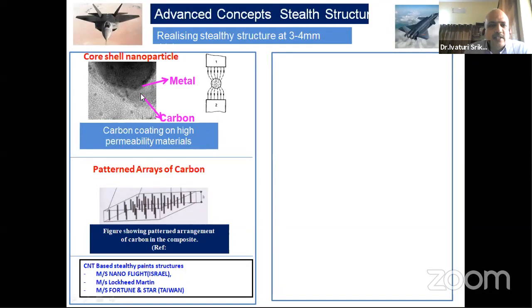Now the latest trend is core shell nanoparticles, where the metal, iron oxide kind of thing, is covered with a thin layer of carbon. This is a carbon layer, and the core is having the metal. So there are certain synthesis methods to realize it. It is like a combination of ferrite and carbon, where you can get both low frequency and high frequency absorption without any weight penalty. So this is the latest trend in the area of stealth with the carbon nanomaterials.